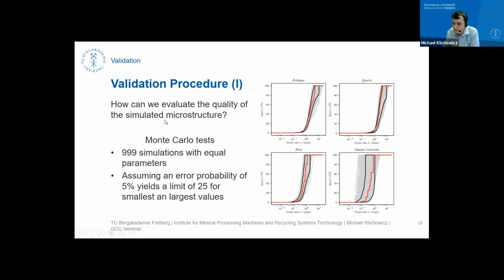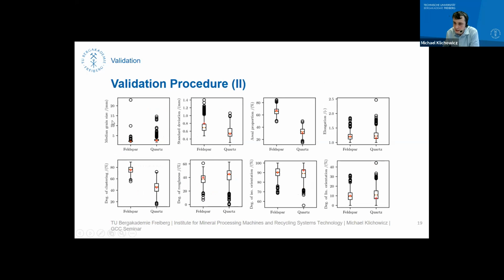But we can dig further in such statistics. For example, we can use those statistics and Monte Carlo tests to evaluate the measures of the QMA, for example, the median grain size or the standard deviation of the grain size. And here we have box plots of the 999 simulations, and in red, that is the real tested microstructure. And we see here again that our real microstructure is in the range of what we have simulated with our model. However, that is still hard to compare, since this approach is linked to these QMAs. If somebody else uses other approaches to characterize a microstructure, other figures would result.